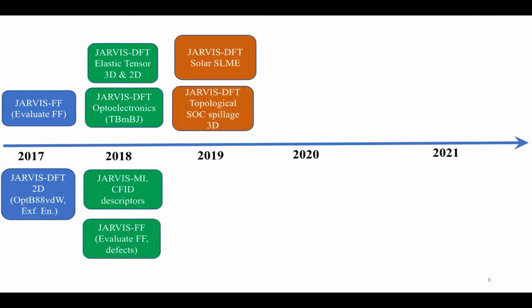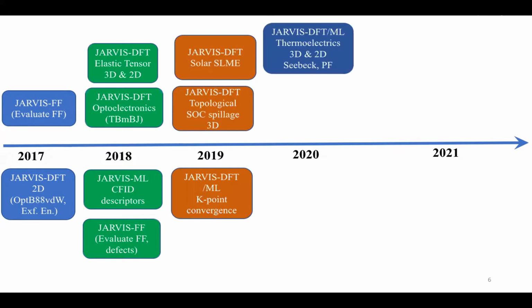And we came up with the spin-orbit spillage criteria, which basically compares the wave function with and without spin-orbit coupling to check whether a material is topologically trivial or non-trivial. And we applied it to 3D materials, both metals and semi-metals. In 2019, we had a k-point convergence paper with density functional theory and machine learning. In 2020, we applied this DFT and ML hybrid approach to thermoelectrics, for 3D and 2D materials.